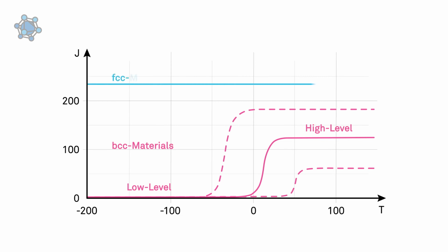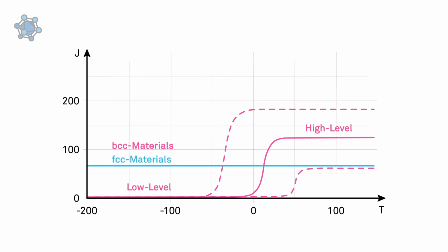In contrast, materials with a face-centered cubic structure have a virtually constant Charpy impact work, so they can absorb pretty much the same amount of energy regardless of temperature. They remain just as ductile and tough throughout, and they are therefore very suitable for low temperature applications. If the material state is changed, for example, by hardening in the case of steel, or if we have a steel with a high carbon content, the kV shifts downward and the material reacts very brittle regardless of the temperature.